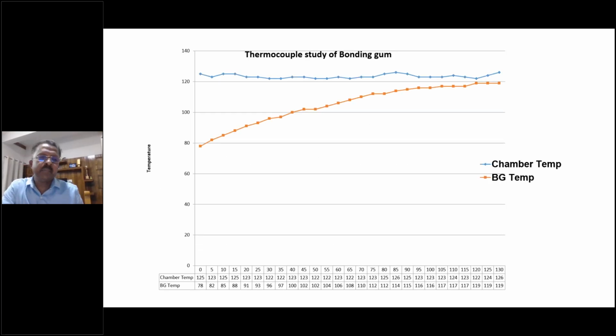This is the temperature-time data. The red is the bonding temperature inside the tire in the electric chamber. And the blue is the chamber temperature. The chamber temperature, we know the chamber is 125 degrees centigrade. It is almost constant from the beginning, time 0. The first is time: 0, 5, 10, 15. We are noting temperature up to 130 minutes.